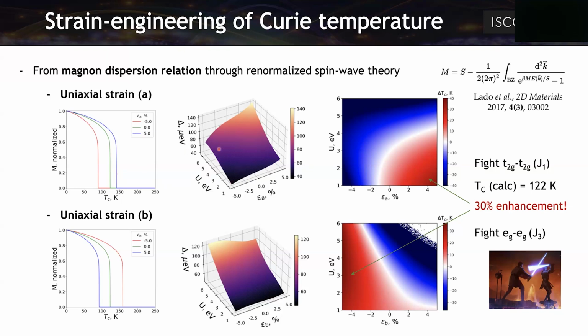We calculated also the evolution of the magnon gap, which I mentioned around the gamma, and we can observe this nice trend. For example, in this case, the magnon gap is being increased when we are increasing the Hubbard U in the calculations for this kind of strain. But this is not translated into an enhancement in the Curie temperature, because in this area we are favoring antiferromagnetic interaction. When we are favoring antiferromagnetic, it's competing with this anisotropy in the material, and we are not increasing the Curie temperature. We need to be in this region here. This is more like just performing expansion of the material, and the temperature will increase.